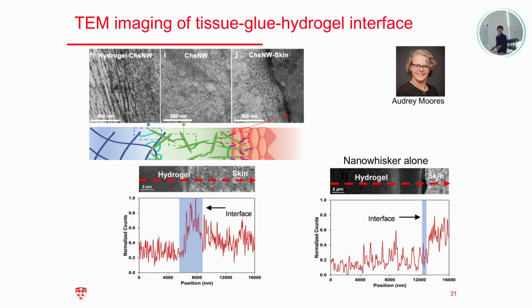So what's going on here? Why, in this case, can the nanoparticle, nanowhiskers, do the job? So here we have teamed up with the chemists at McGill, and we use the transmission electron microscope to really see very thin sections of the skin hydrogel samples. That is a quite challenging task to do in terms of doing the TEM on the skin sample. So in this result, hopefully you can clearly see that instead of the classical picture of nanoparticle adhesion, where you have a nanoparticle in between binding the two matrices on both sides,